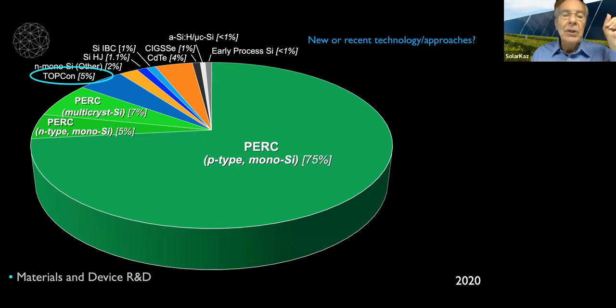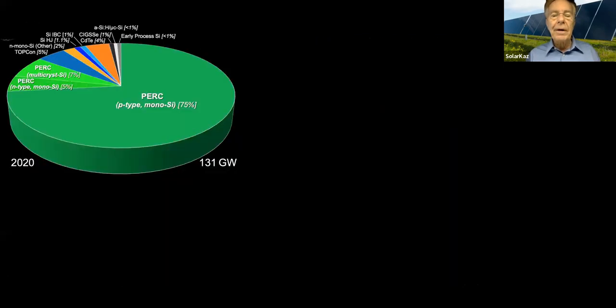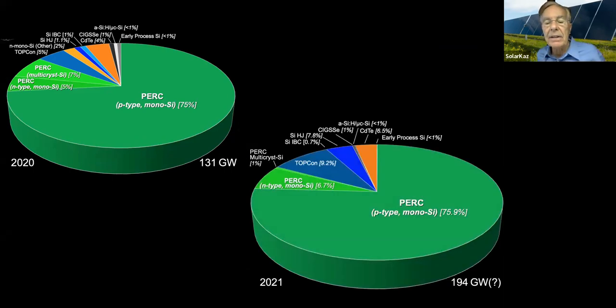But technology advances, and something is coming up here called the TOPCon cell. And if you see on this record, it's about 5% of this. This is a technology that's grown out of Europe. It's still a simple technology that looks very, very much like PERC, but it's starting to replace it. So here's that same 2020 shipments, 131 gigawatts. And here's what it looked like last year in 2021 from the data that's come out, where you can see that TOPCon now is starting to take over a little bit.